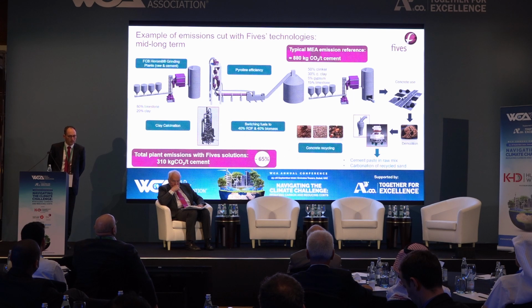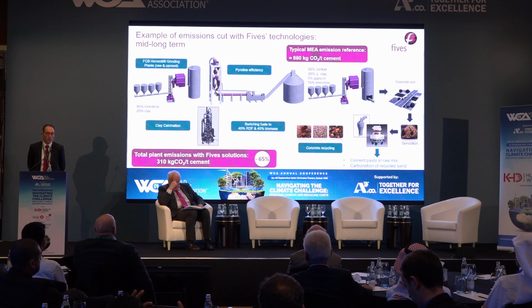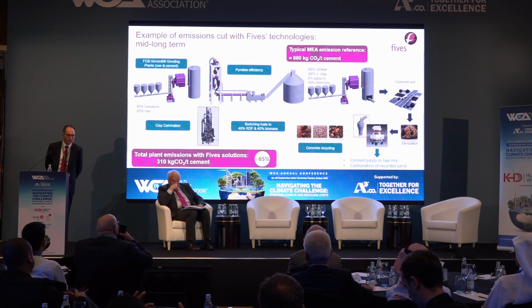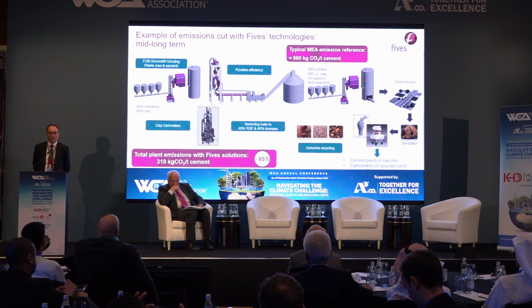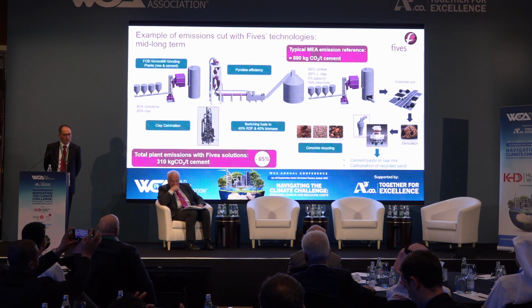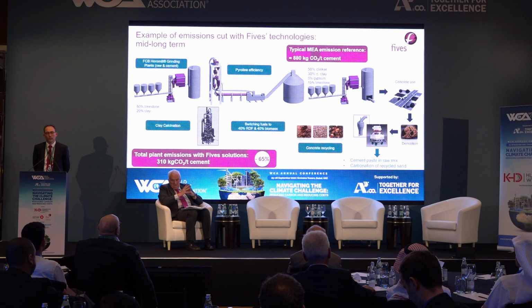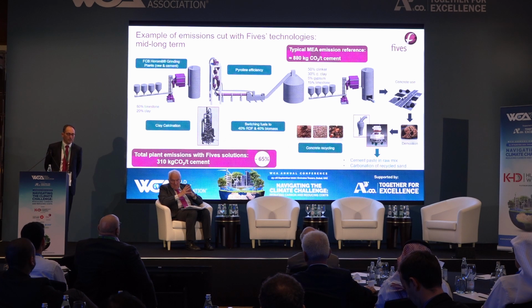One on the bottom left is the clay calcination. I will go more in detail, but it allows us to produce what is so-called LC3, cement containing only 50% clinker. So it's a significant saving in terms of CO2 emissions. Also, the evolution of the pyroprocessing technology to increase the possible amount of alternative fuel use in a cement plant, whether it is biomass or RDF.